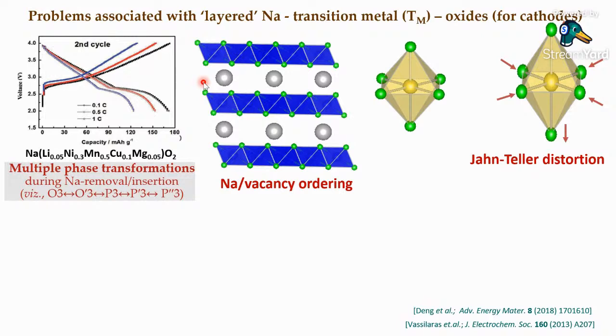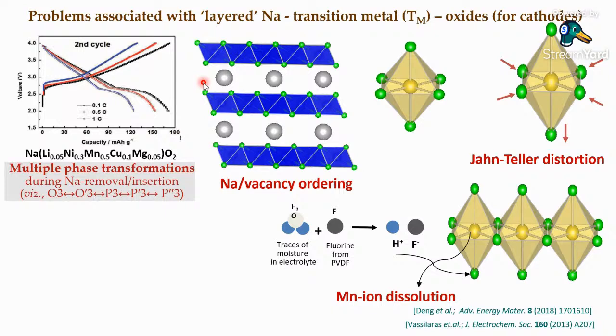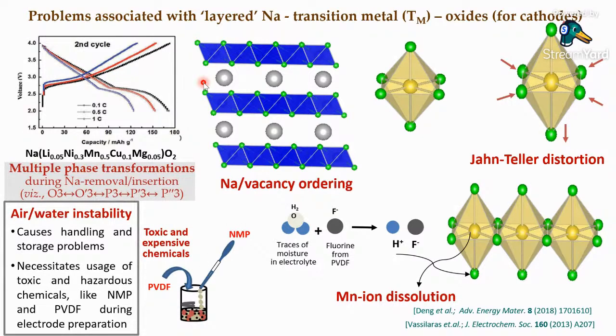There can be Jahn-Teller distortion in the Jahn-Teller ions, and the presence of manganese leads to another problem in addition to Jahn-Teller distortion, that is manganese dissolution in the electrolyte. And as I told, one of the major problems is the air-water instability in the sodium layered transition metal oxides, and that can make the structure deteriorate very, very fast, and the structure can become absolutely useless unless it is protected from exposure to air and moisture.